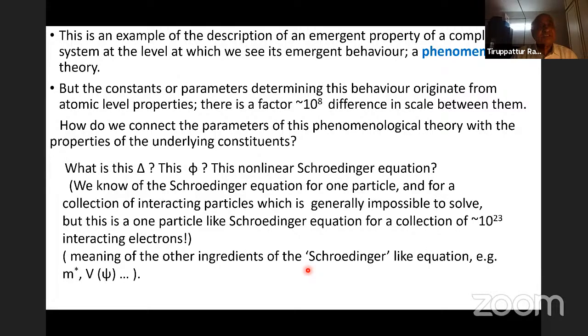This equation is somewhat like that of a single particle, single quantum mechanical particle. They showed that the solution of this equation can describe a state of zero electrical resistance and non-zero phase rigidity with the phase being the same throughout the superconductor when the magnitude of this wave function delta is non-zero. They also worked out, assuming physically motivated parameters for this Schrödinger-like equation, many consequences for the substance which satisfies this equation, and they showed that it agrees with what we see. This is an example, perhaps the most successful example, of the description of an emergent property of a complex system at the level at which we see its emergent behavior. This is called a phenomenological theory.